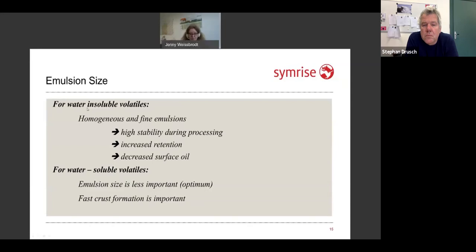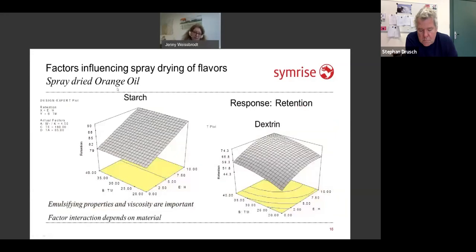For water-insoluble volatiles, you need a homogeneous and fine emulsion because this will give you a high stability during processing. This means that the first few milliliters you spray dry will have the same quality as the last milliliters you spray dry. So you prevent a demixing, a coalescence, a breaking up of your emulsion during the processing. Thereby, it will increase the retention because of this nice and fine distribution of your active within the matrix, and it will even decrease the surface oil. You can see this here for the orange oil.